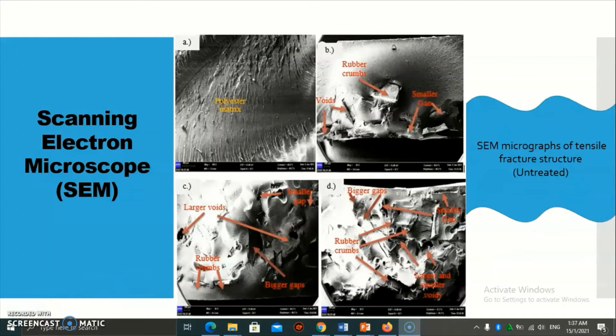Okay, for the next part, I want to explain the figure for the scanning electron microscope of the tensile fracture structure for the untreated. As you can see here, this figure is pure polyester, 5%, 10% and 15%. There is nothing in here because it is pure polyester. For the 5%, there is a little rubber in it, and a few voids and smaller gaps. For the 10%, there are larger voids, smaller gaps, bigger gaps, and the rubber crumb increases. For the 15%, the rubber crumb increases, as well as bigger gaps, smaller gaps, and larger and smaller voids.